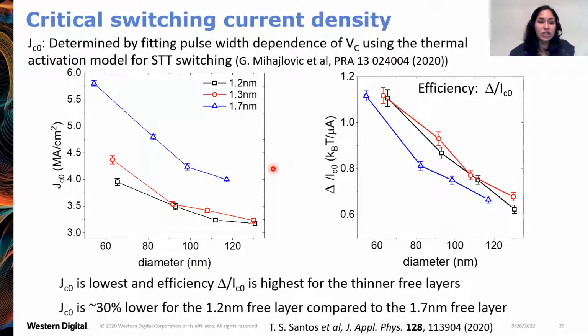The critical switching current density Jc0 was found by fitting the pulse width dependence of the critical voltage using the thermal activation model for spin transfer torque switching. And what we found is that these thinner free layers have a 30% reduction in the critical switching current density compared to the thickest free layer of our study, this 17 angstrom free layer. So then if we look at spin transfer torque efficiency, this is a common figure of merit in MRAM. It's defined as the thermal stability factor delta over the critical current. We find that it's the thinner free layers that have the highest efficiency because they're showing the lower switching current density, yet maintaining high thermal stability.